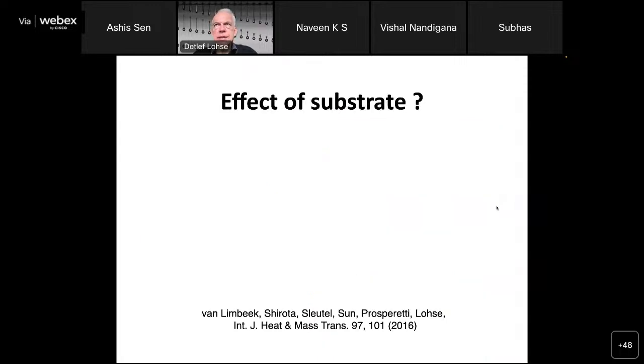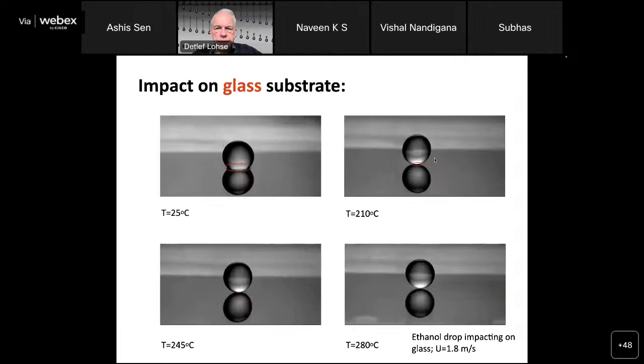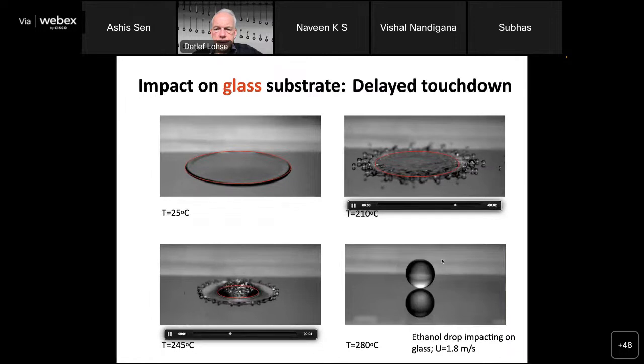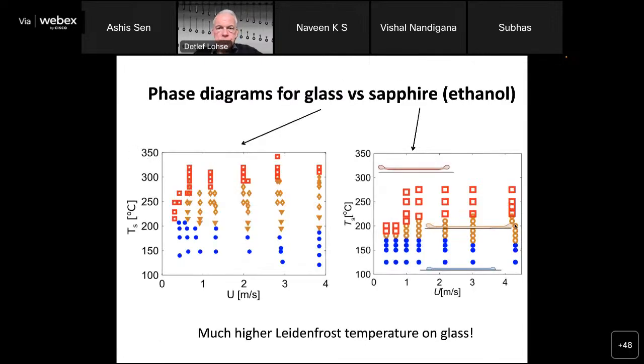So this was the effect of the liquid, but now what's the effect of the substrate? We want to compare glass versus sapphire, which has very different thermal conductivity. So here you see the impact on glass for different temperatures, the glass impact here. So I've shown similar movies before. Now what's happening for impact on sapphire? Well, here is ethanol in both cases. On the left you have glass, and on the right you have sapphire.